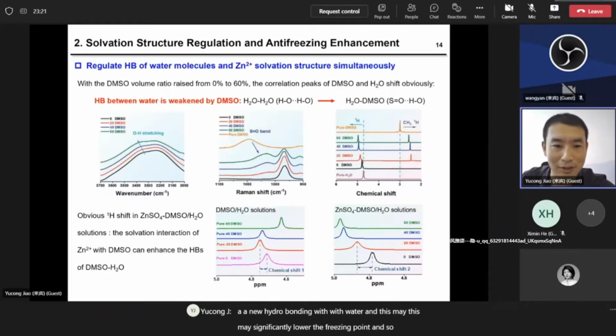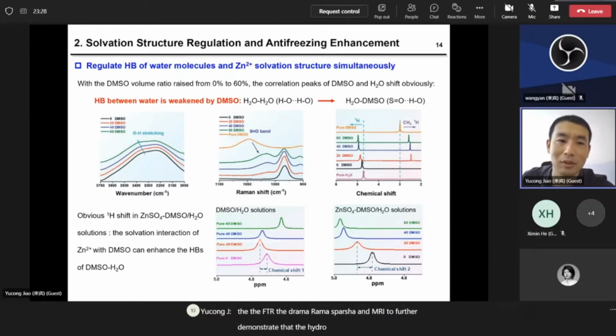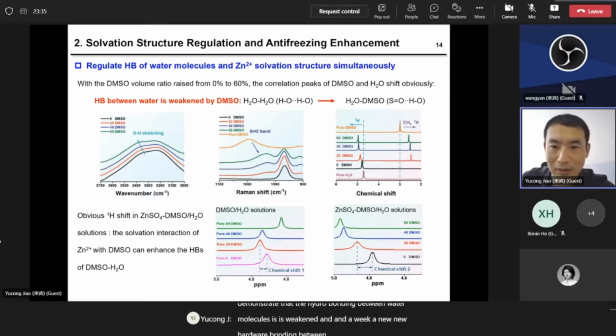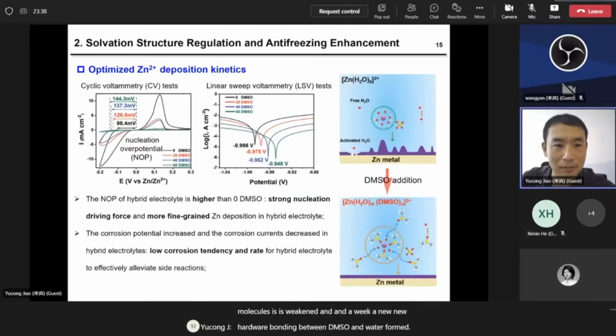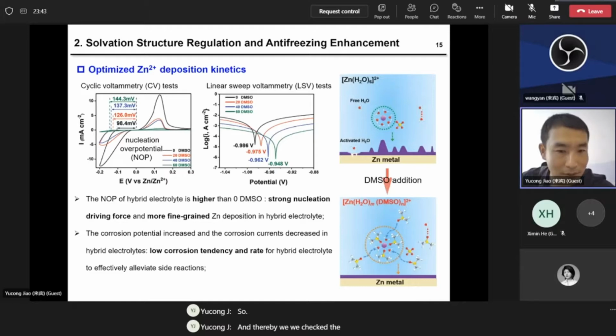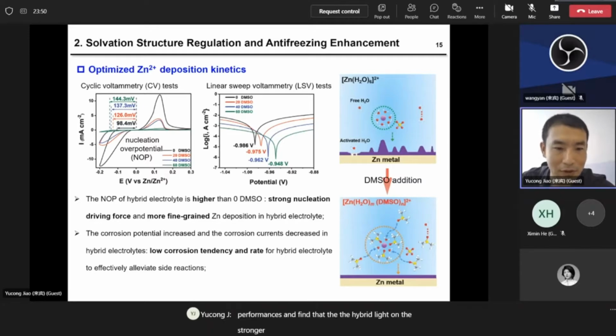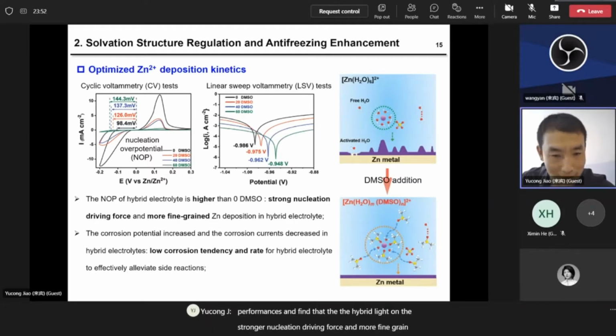And so we use the FTIR, the Raman spectra, and NMR to further demonstrate that the hydrogen bonding between water molecules is weakened, and a new hydrogen bonding between dimethyl sulfoxide and water is formed. So thereby we checked the electrochemical performances and find that the hybrid electrolyte owns a stronger nucleation driving force, a more fine-grained zinc deposition morphology, low corrosion tendency, and rate.